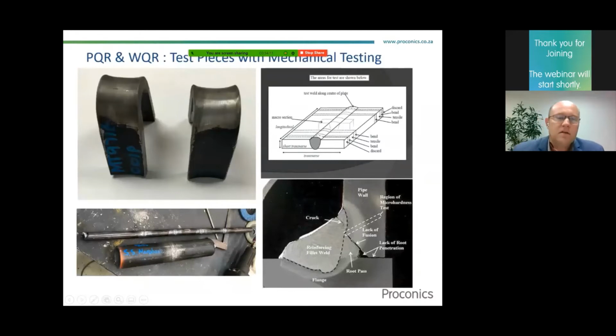So as part of ISO 3834 and the fabrication standard, qualified procedures and qualified welders need to be in place. This is to ensure that sound welding can be produced. In the photos below, you will observe that on the top left, these are two bend tests conducted to qualify a procedure qualification record in accordance with ASME Section IX. On the top right, this is a sample for standard testing to qualify a procedure qualification record in accordance with ASME Section IX. It gives you the quantities of mechanical tests as well as the locations of samples to be taken.